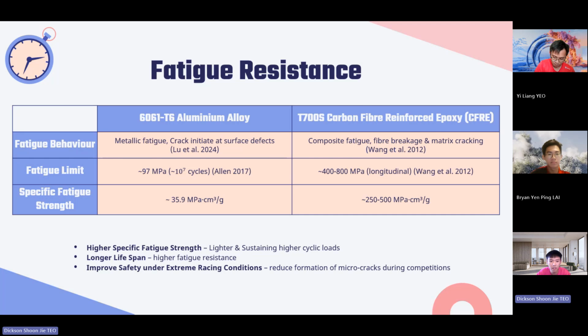Fatigue resistance is another key factor. Aluminium typically has a fatigue limit of about 97 megapascal, whereas CFRE can withstand up to 400 to 800 megapascal under cyclic loads. This translates to a much longer lifespan under extreme racing conditions.